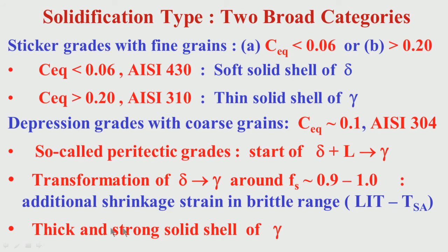So, here we have a thick and strong solid shell of austenite. At the end of the solidification, it is already austenite. We have a thick shell because micro segregation is less, because the initial solidification was through delta. So, a relatively thick solid shell, the mushy zone is thin, and a strong solid shell because it is austenite. So, there are two broad categories of solidification characteristics and cast structure depending on the chemistry of the particular alloy. This we have to keep in mind.